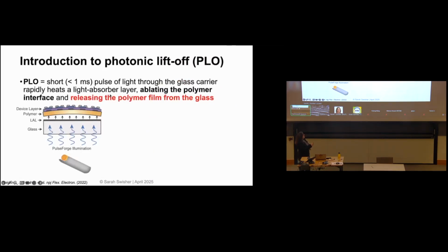And then if I take that thing and I flip it upside down, and here's my illumination now, I'm going to illuminate from the bottom through the back of that glass substrate. That illumination is going to get absorbed in this metal light absorber layer, just like it was absorbed in the metal gates. But now, if that metal is a blanket layer everywhere, it means the light is never going to hit my device up here. It's all getting absorbed in this light absorber layer. So I don't have to worry about the light heating up my device anymore. It's done. Right? It's not going to get changed anymore.